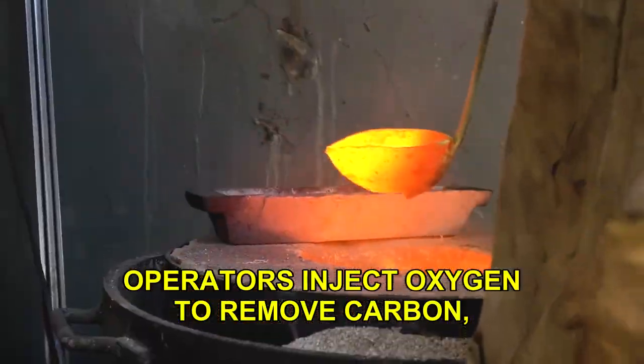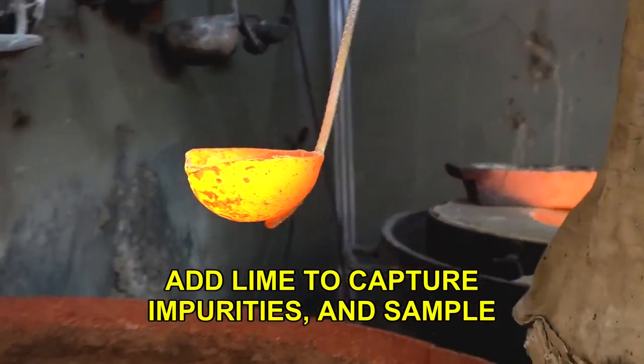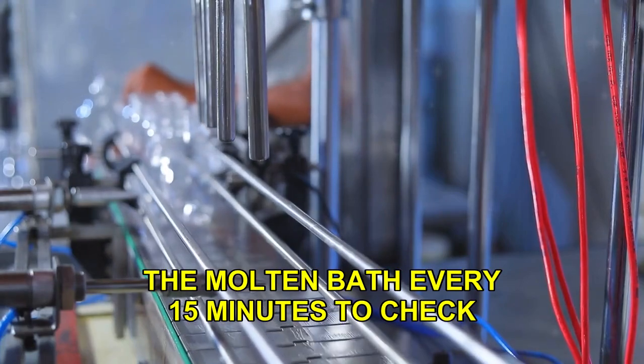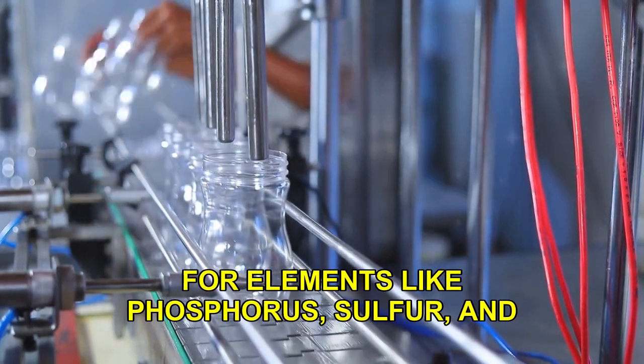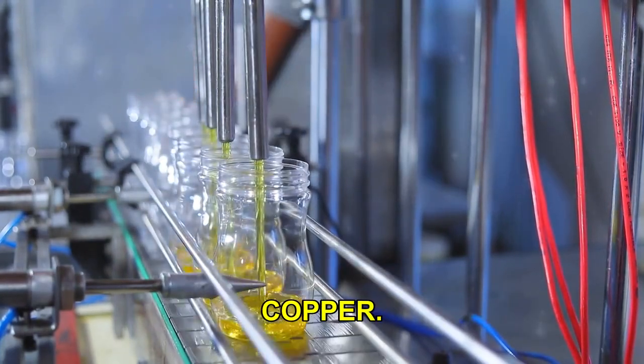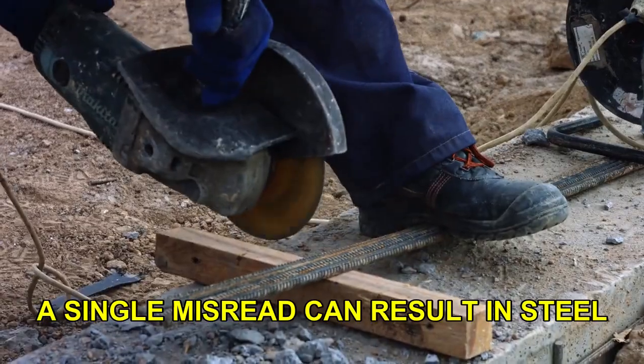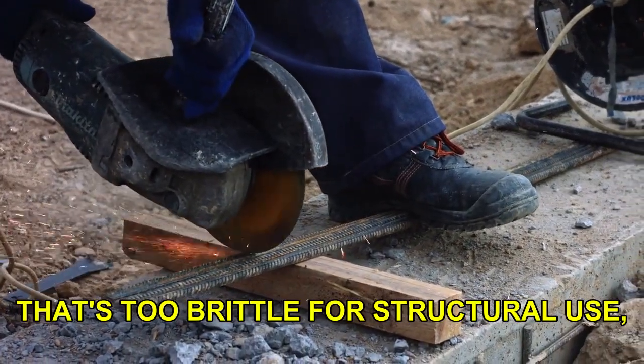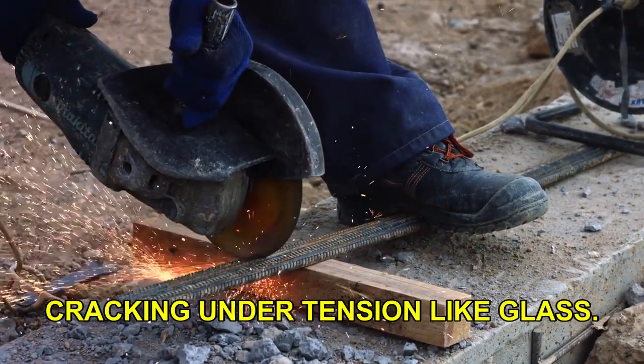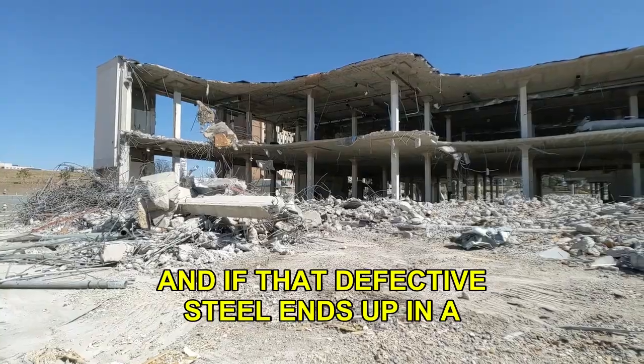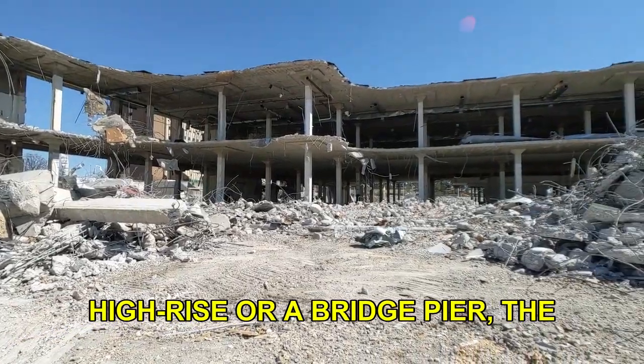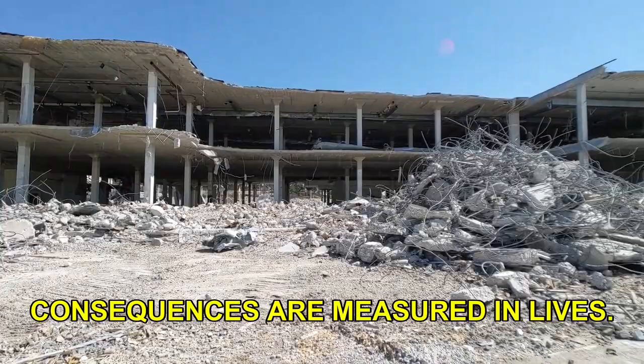Operators inject oxygen to remove carbon, add lime to capture impurities, and sample the molten bath every 15 minutes to check for elements like phosphorus, sulfur, and copper. A single misread can result in steel that's too brittle for structural use, cracking under tension like glass. And if that defective steel ends up in a high-rise or a bridge pier, the consequences are measured in lives.